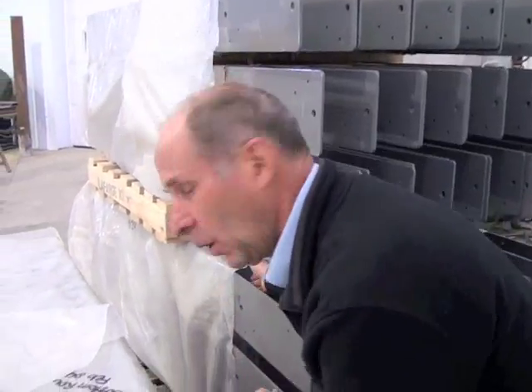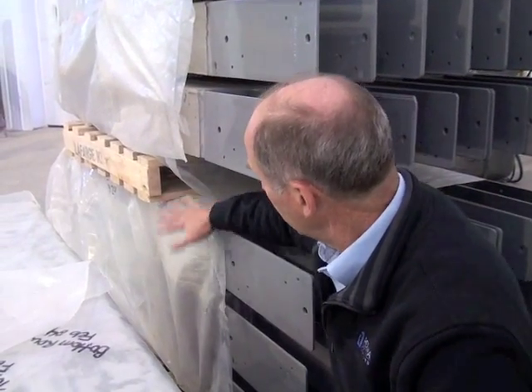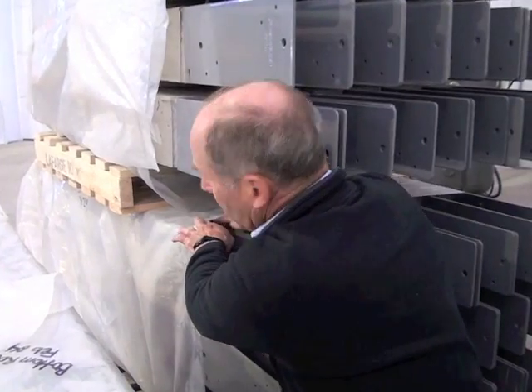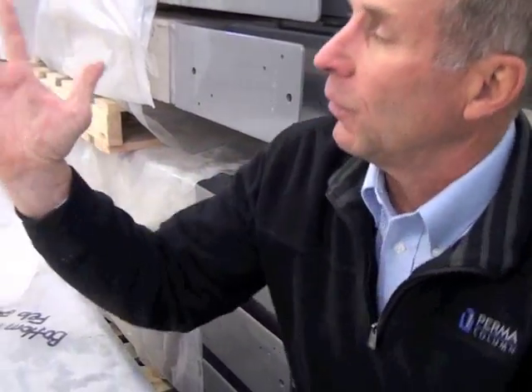To show you something, how important this is. These were poured yesterday. We put curing pads inside of these cure bags. And if you stick your hand in here, you will find out they're wet. It's warm and it's wet because the curing process we want to take a real long time, a 7-day period, and we want it to come slowly so that the columns will come up to strength and be a 10,000 PSI concrete. And just to give you a frame of reference, a typical sidewalk might have 3,000 PSI strength concrete, and Perma-Columns have 10,000 PSI.